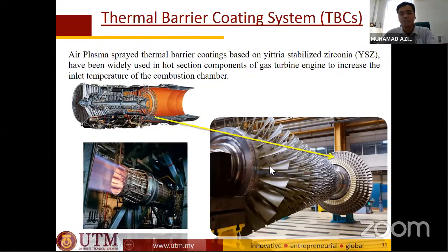So the main component that runs the engine is basically the turbine blade. So this is basically the turbine blade, which they usually make from Inconel nickel superalloy. They also make from titanium alloy, depending on the area. For the combustion area, the blade is made mainly from Inconel or nickel superalloy. But lately we're talking about the problem of high temperature applications. We're talking about oxidation. So therefore, there is a need for coatings of this blade.